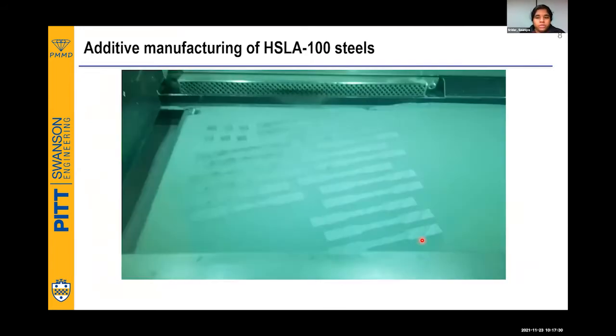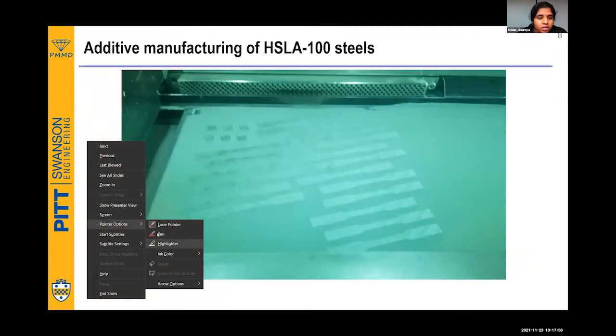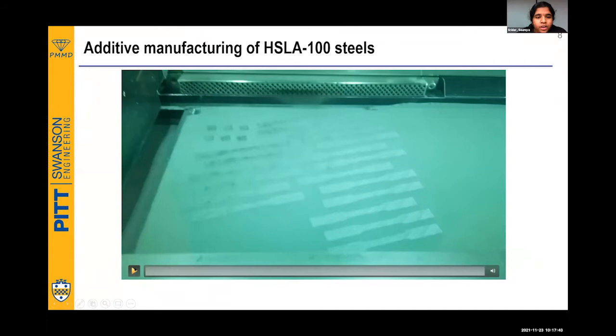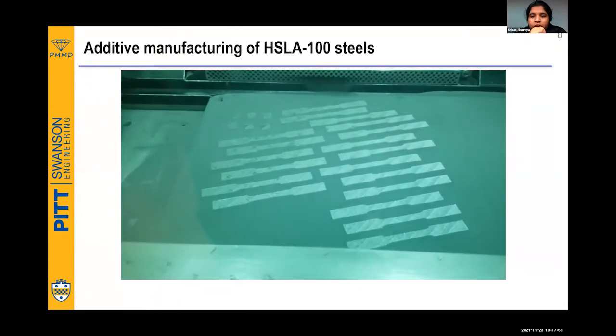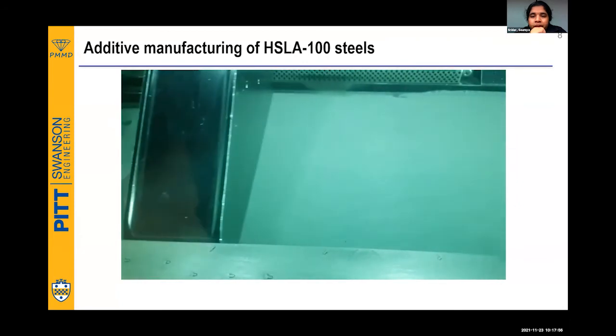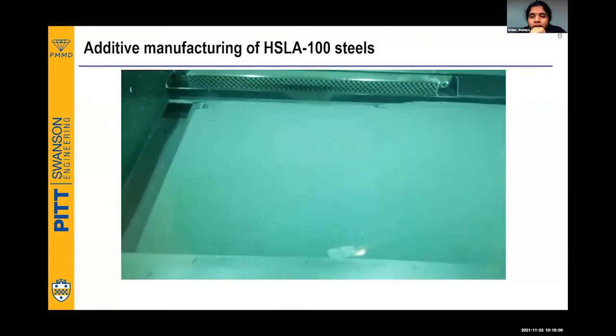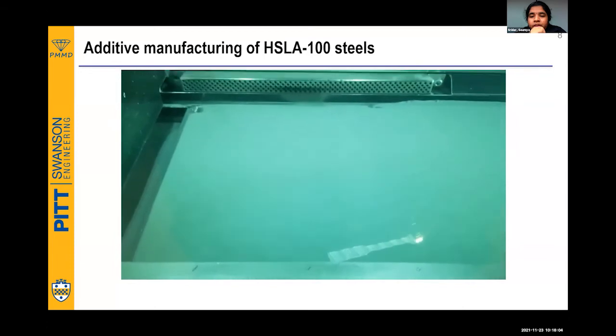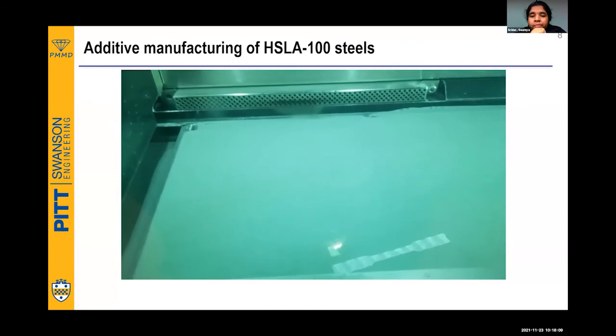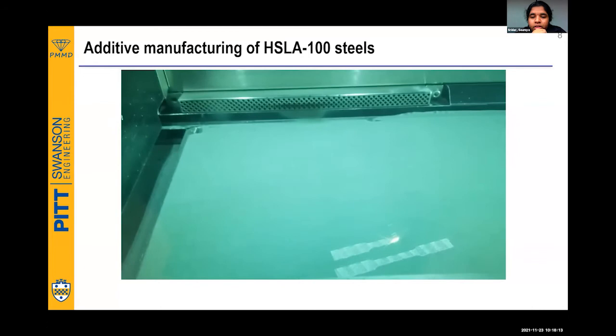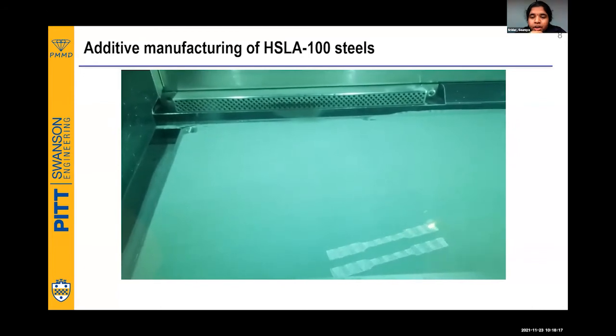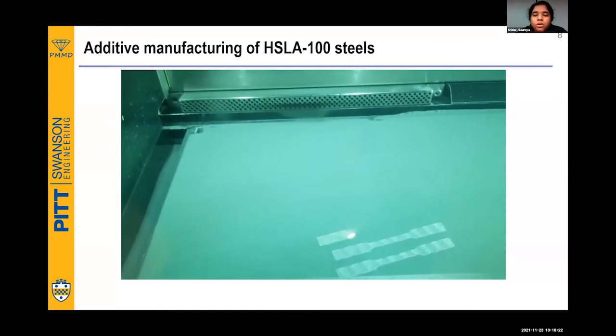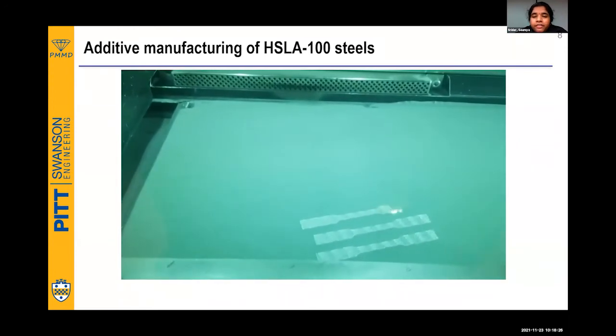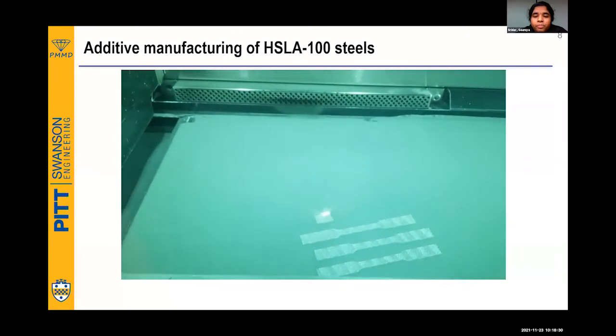So instead of showing some schematics, I thought I could play a video here which was shot during our printing of the HSLA steel powder. Now you see that the recoater is going to spread a uniform layer of the powder, and the laser is going to hit. We are trying to build tensile bars here. Our build plate dimension is 250 mm by 250 mm. If you notice carefully towards the end, there is something that goes around along the periphery. That fast thing is done to create a better surface finish, which is called a contour print.